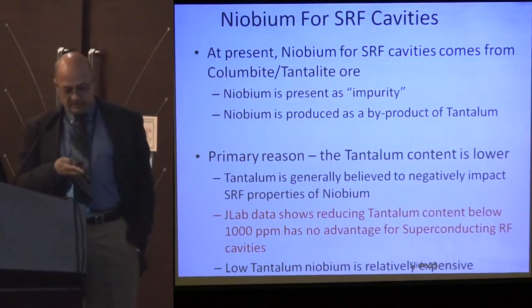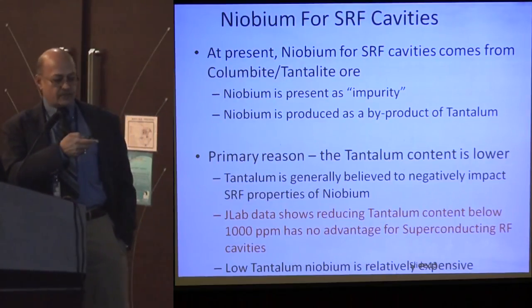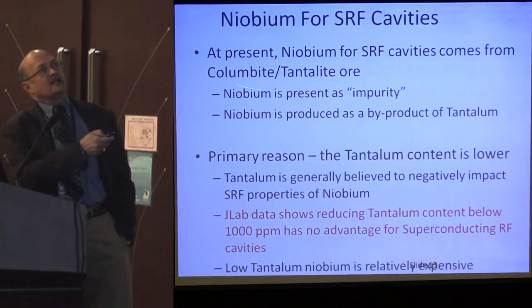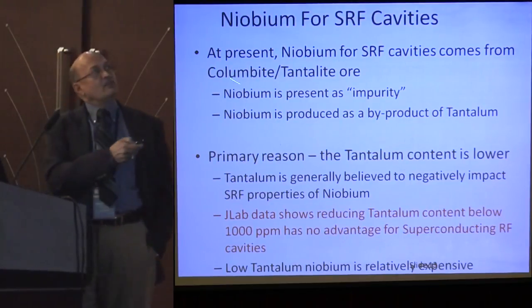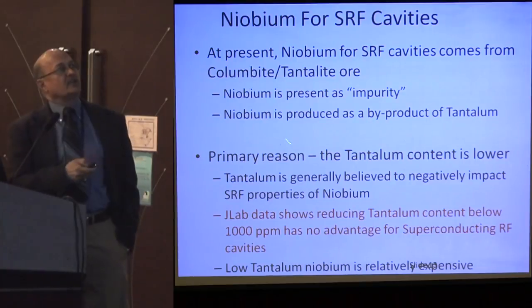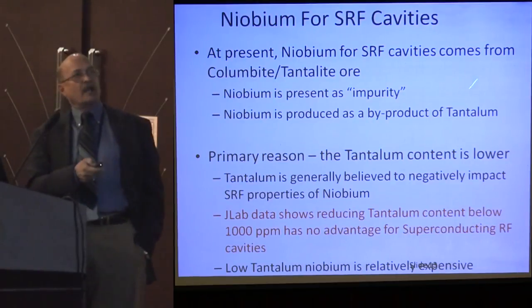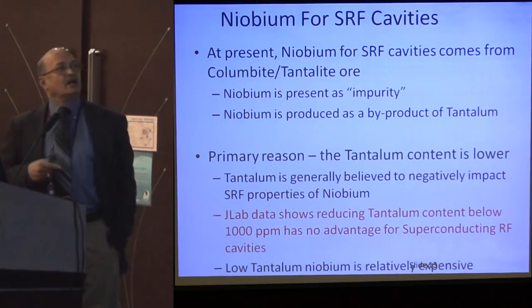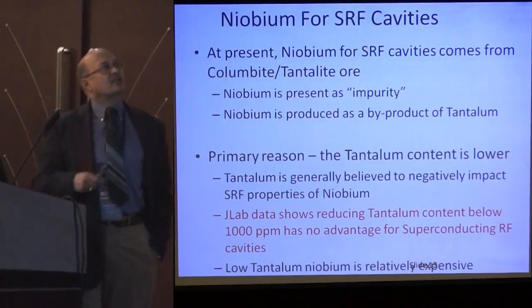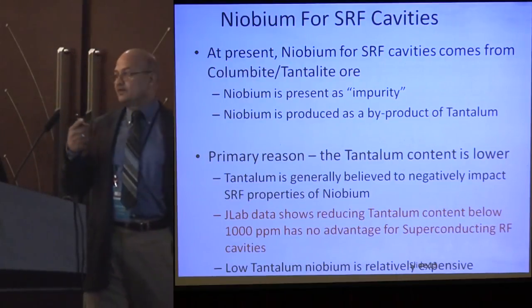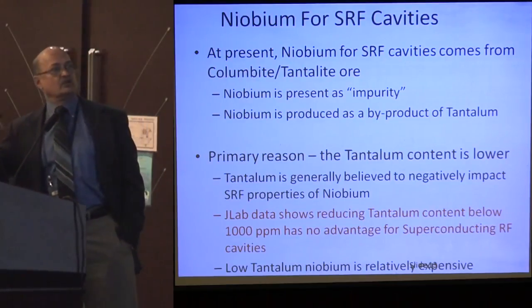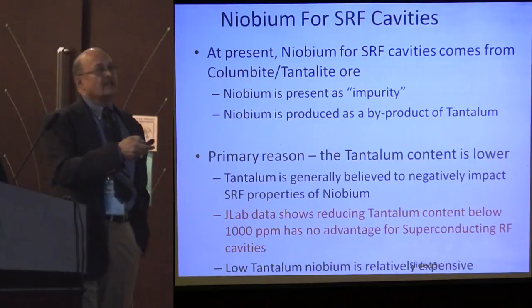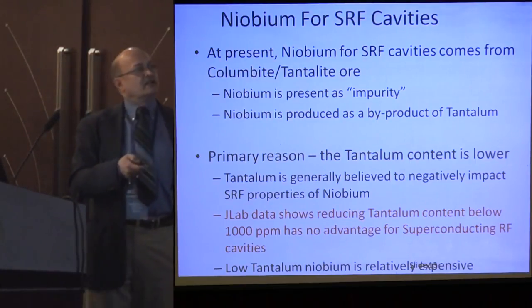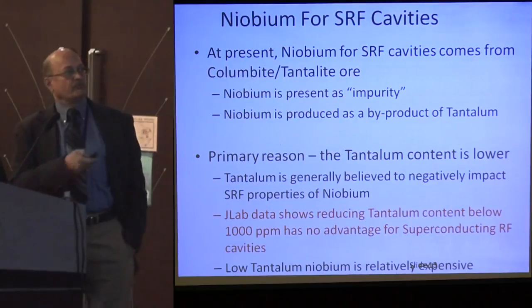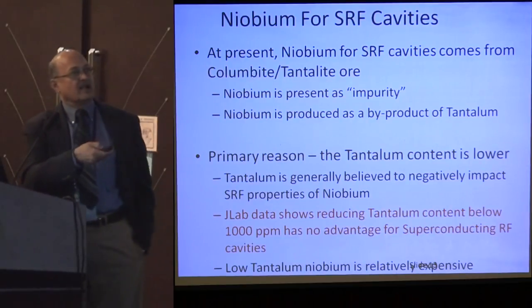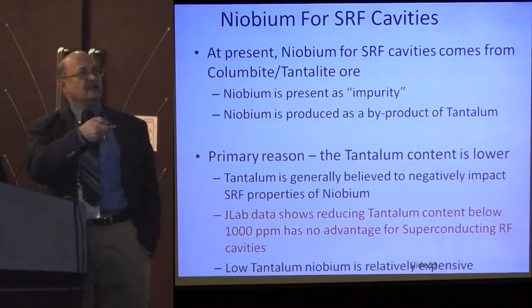And at present, the niobium comes from a columbite-tantalite ore. Niobium is present in this ore as an impurity. Niobium is produced as a byproduct of tantalum. The primary reason for using the columbite-tantalite ore instead of the other ore known as pyrochlore, which I'll explain a little later, is that the tantalum content is lower in this ore, because it's a byproduct, so you can actually spec whatever you want in that.